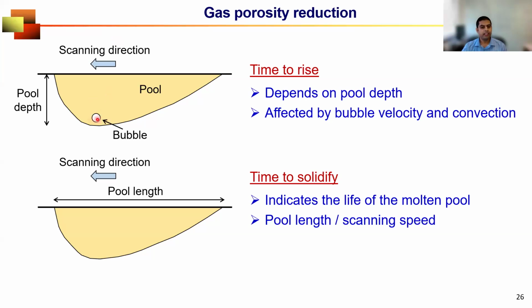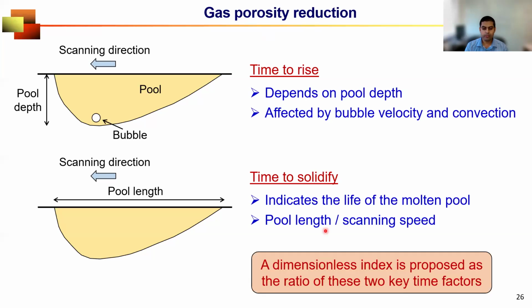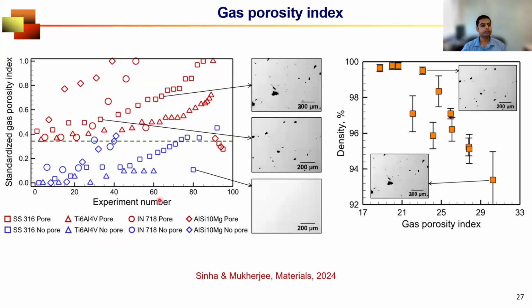So the time it takes to rise up, time to rise, and the time the molten pool takes to solidify, both are important. If time to rise is significantly higher than the time to solidify, then definitely you are going to form porosity. So what we did, we tried to calculate these 2 times in additive manufacturing and come up with their ratio and propose a dimensionless index. What did we find?